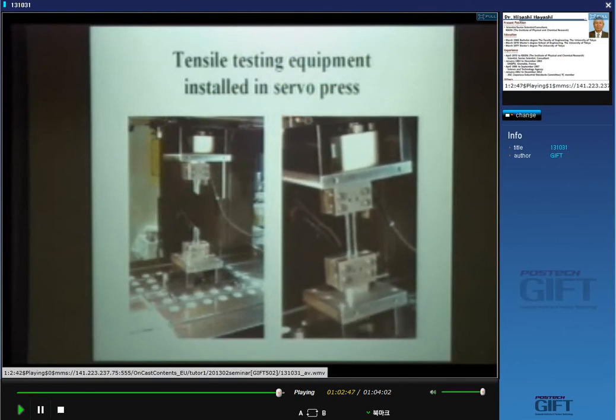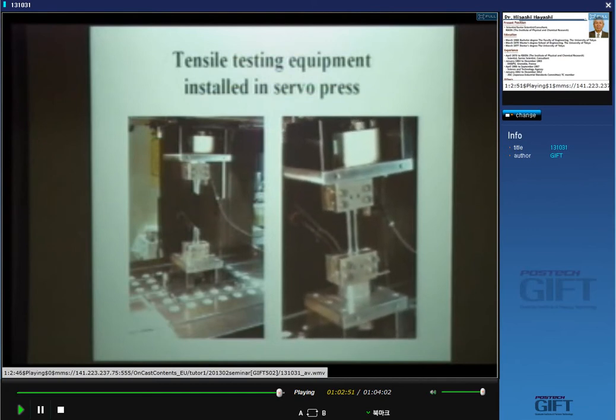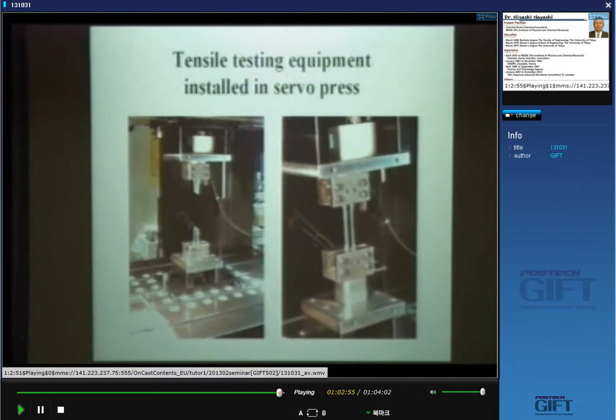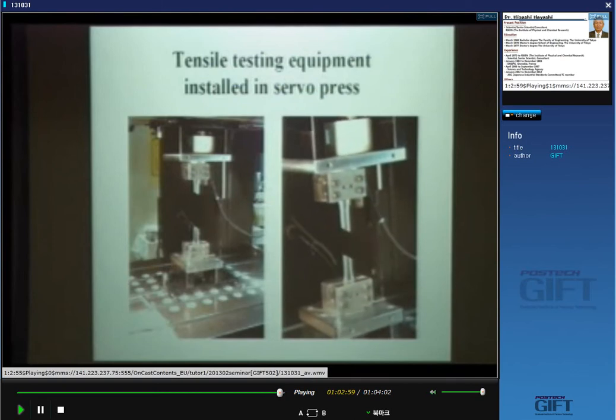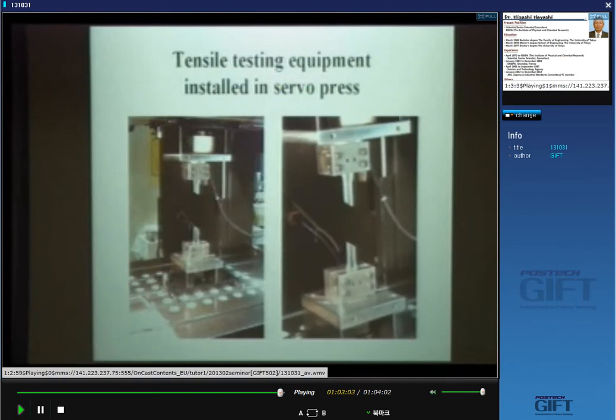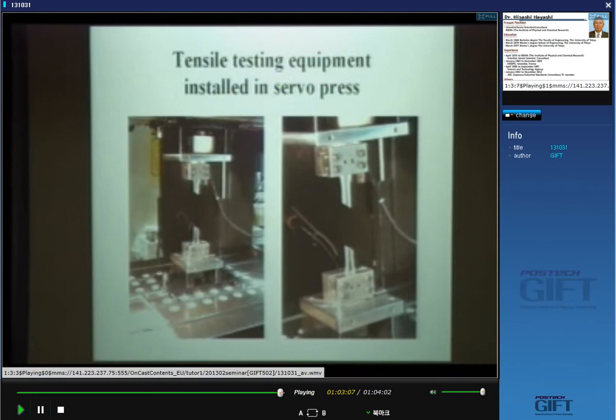After then, starting the tensile test, like this. So we install this tensile equipment into the servo-press, and also we measure the deformation with high-speed cameras, synchronized with the high-speed camera and load cells, and we obtain the stress-strain curve under very high deformation rate for four types of high-strength steel sheets, aluminum alloys and stainless steels. And as a case, we also need the deformation rate sensitivity of frictional behavior. At that time, we could not do it.